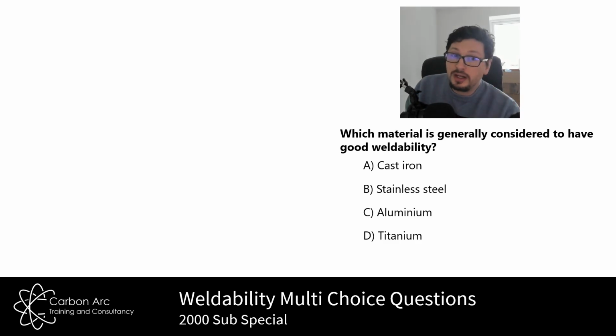Aluminium, some grades of alloy just don't weld, I think like the 7000 series and stuff like that. We see them as cracking fairly easily because of hot cracking. Titanium, stainless steel, are they fairly close? I would say that titanium needs a little bit more control, because you've got not only the purging issues to stop it oxidizing, but also the cleanliness issues to stop porosity and things like that. Any contamination, titanium tends to cause us issues in the process itself. So my best answer there is stainless steel being good weldability.